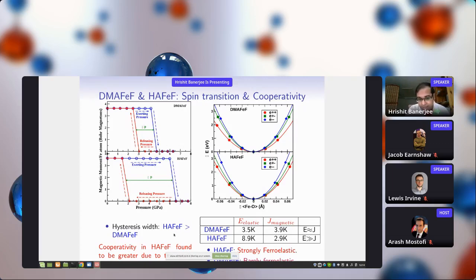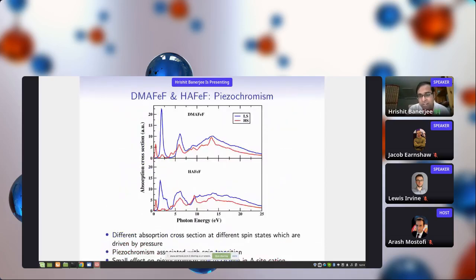And this is due to the fact that hydroxyl ammonium iron formate is very strongly cooperative and very strongly ferroelastic, whereas dimethyl ammonium iron formate is less cooperative and less strongly ferroelastic. And we can also show piezochromism by calculating the absorption cross-section in both these materials. And we find that they are expected to have very similar color changes.